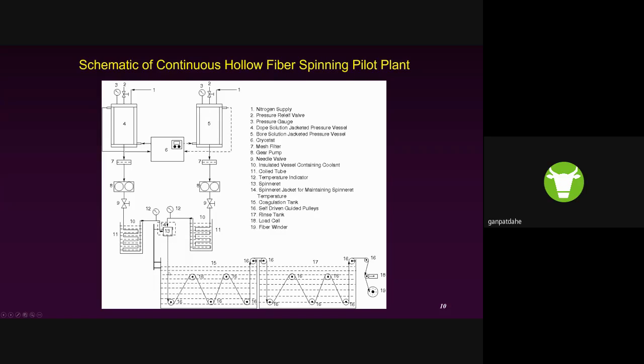You can vary the structure by varying the air gap, and the fibers pass through the coagulation tank. In the coagulation tank, one has to make sure that the fibers are completely precipitated. Later on, they pass to the next tank, called the rinse tank, where the residual solvents are removed, and later on they go to the fiber winder, the roll. So this is the typical schematic for the hollow fiber making process.